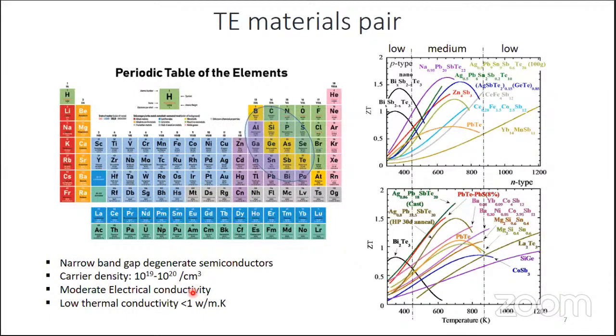Electrical conductivity will be very moderate, and most importantly the thermal conductivity. So this is very critical. Preferably it should be less than 1 watt per meter Kelvin. Most of the materials show values in this range, or if it is a little high, as this value goes up and up, the thermoelectric material leg height required to create a delta T will continuously increase. These are some of the high performing thermoelectric materials in P and N type.